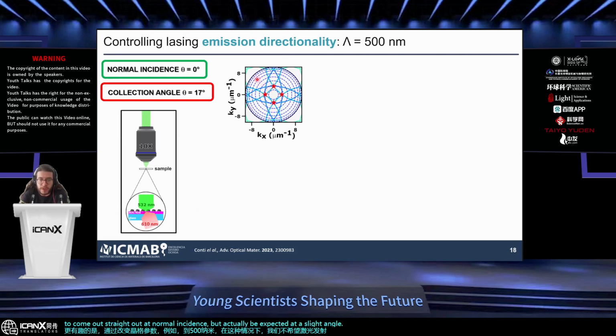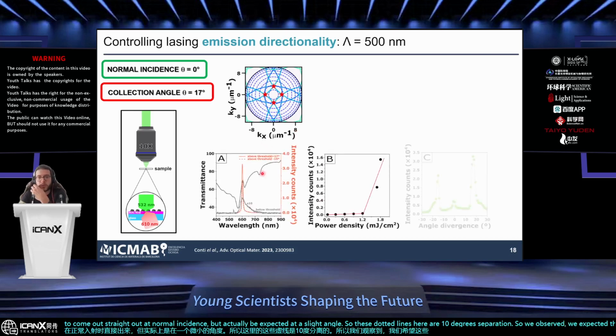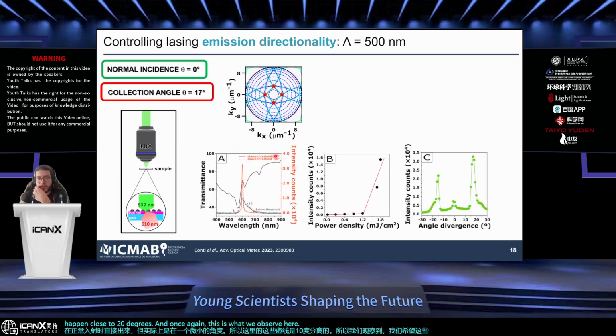So these dotted lines here are 10 degrees separation. So we expected this to happen close to 20 degrees. And once again, this is what we observe here, at plus 17 and minus 15, that we do observe this sharpening and intensity increase in the emission of the rhodamine B. So once again, the typical threshold plot for a lasing emission and the divergence angle.